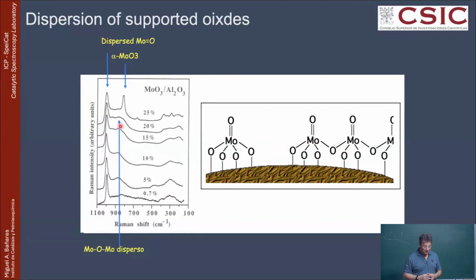You go to 25% and then you get new Raman bands which are sharper, which are stronger. These bands are no longer dispersed molybdenum. This is crystalline molybdenum trioxide. And the nice thing is that while the dispersed oxides are sensitive to ambient moisture, crystalline phases do not care. If you look at this same sample under ambient hydrated conditions, all these bands will change as we saw before into the hydrated one. But the crystalline molybdena will not change.